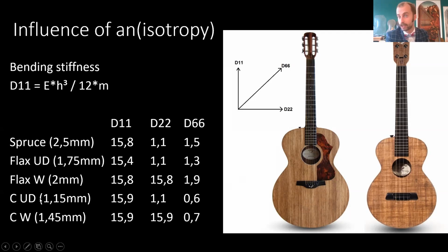It is a very, very stiff and strong fiber. So we need to make it a lot thinner, almost a little bit over 1 millimeter, to have the same stiffness, not strength, the strength will be higher, as the spruce plate here. And then you see that the stiffness in longitudinal direction is similar, also in the transverse direction, but the torsion of the material is a lot lower.